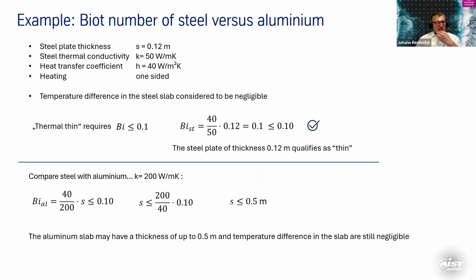So look at a very brief example. Look at steel versus aluminium. When you say thermally thin requires a Biot number of less than 0.1, you ask the question: is a steel slab of 120 mm thickness, 0.12 meter, thin or thick at certain heat transfer conditions? We say here the heat transfer coefficient is 40 watts per square meter Kelvin. And then the Biot number is h divided by k times S, which is 0.1. Okay, this is still in the upper end of being thin. So it is still thin.